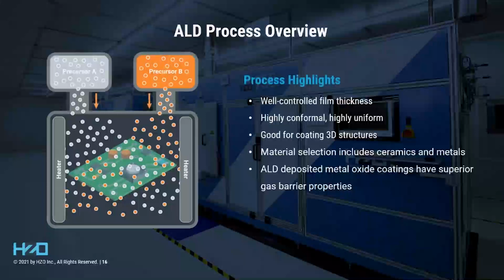The way it typically works, though, is precursor A is flowed into the chamber from the first reactor, depositing an atomic layer on the product, say aluminum. Chamber is purged, and the atomic layer might be modified by a plasma to allow chemical reaction with the next layer. Precursor B is then flowed into the chamber, depositing another atomic layer on the product, say silicon. And the chamber is then again purged, and the atomic layer might again be modified by a plasma to allow chemical reaction with the next layer. And this goes back and forth, applying a single atomic layer each time in repeated cycles until you end up with a coating the thickness you're after.